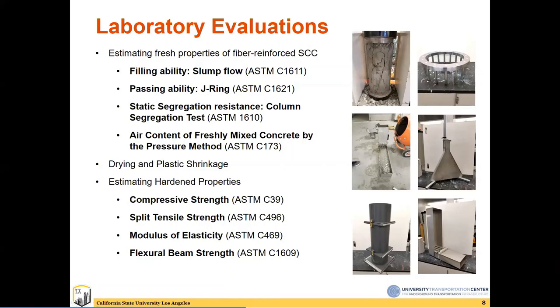Segregation is very important in SCC, and we don't want to have or to see bleeding or segregation in our mix. That's why we do the static column segregation or the static penetration test. And also we are evaluating the air content of fresh concrete SCC mix under different criteria and using different materials.